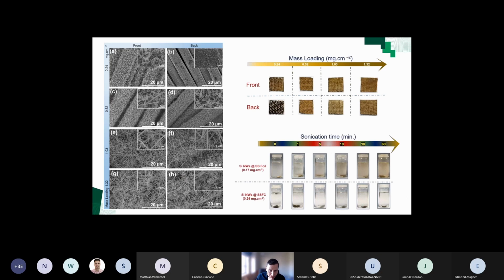We were able to show that quite simply using sonication. If you took a stainless steel foil versus the stainless steel cloth and sonicated it for up to an hour, with the foil the solution becomes progressively darker, and that's related to the nanowires just coming off the foil. Whereas if you do it with the cloth, you get no, or very little at least, nanowires coming off.